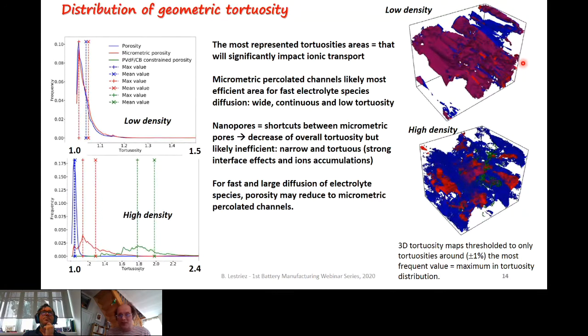Thus, these maps highlight the most represented tortuosities areas, that is to say, the ones that should the most significantly impact the ionic transport. So in these low density electrodes, you can observe in red, the manifestation of the micrometric channels. You can see that they are wide. So here it's 10 micrometer thickness. They are wide, they are straight and low tortuosity. So likely they will be efficient areas for electrolyte species diffusion.